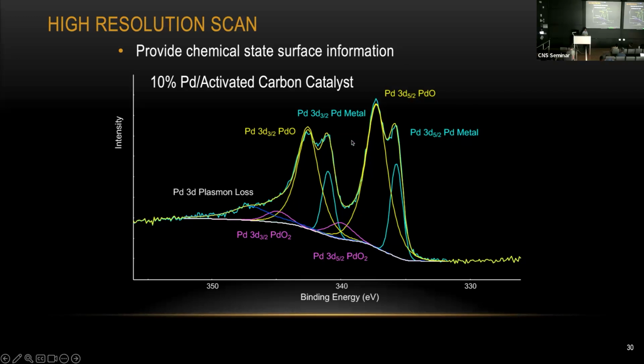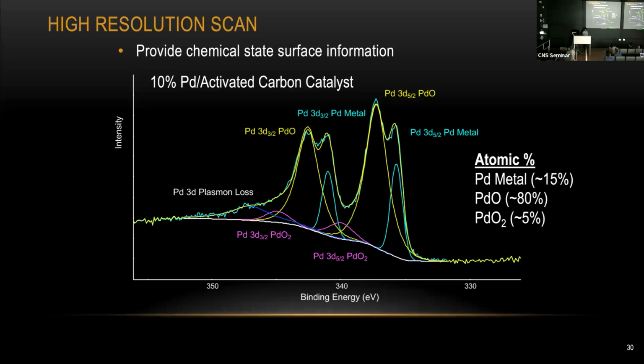If you want to get some nice molecular information, you probably want to go to my colleague Arthur, who gave a talk during the first week of the seminar. But depending on the sample you're working on, for instance, a metal cannot give you a Raman signal, so you still need to come to the XPS and do some high resolution scanning and a good fitting. Based on your fitted peaks, we can also get some quantification. Based on the signal we are fitting here, we only have 15% pure metal. The rest is all oxide with two different oxidation states.